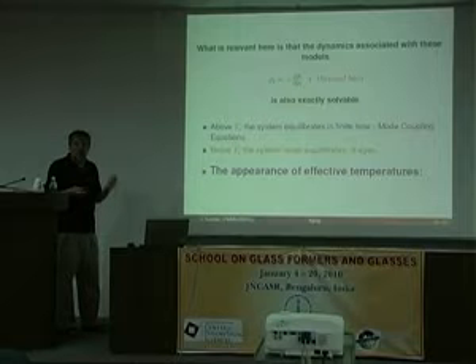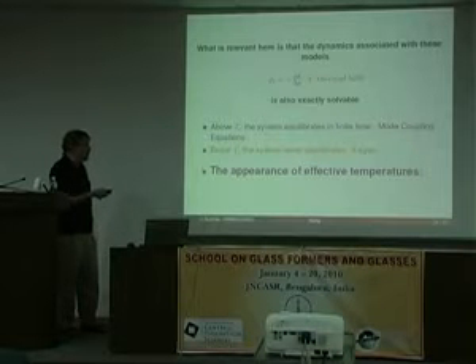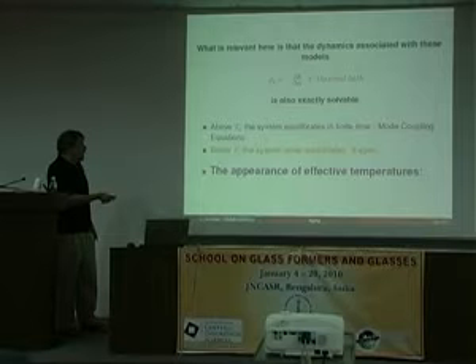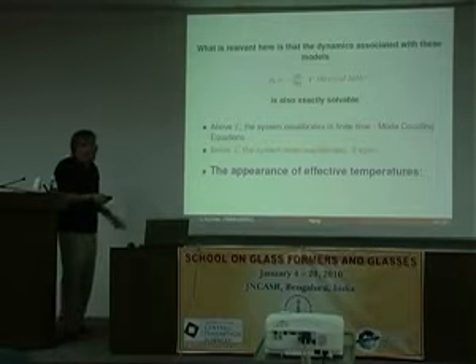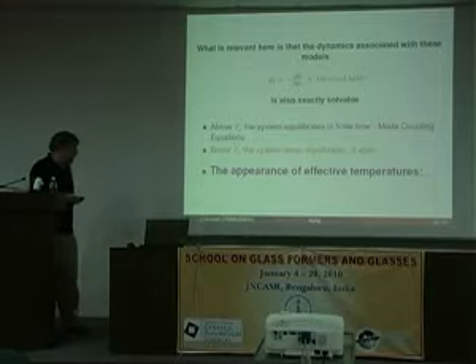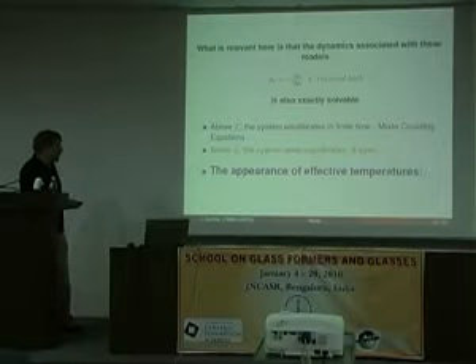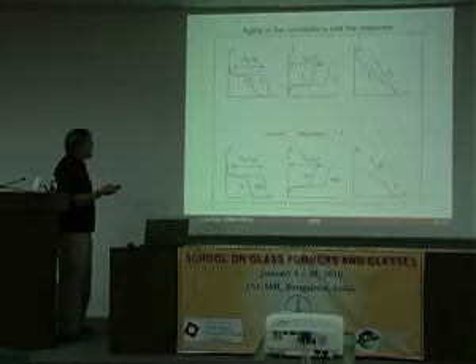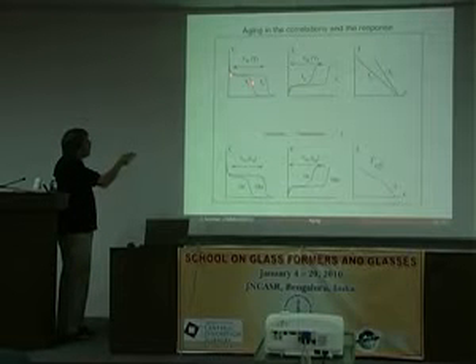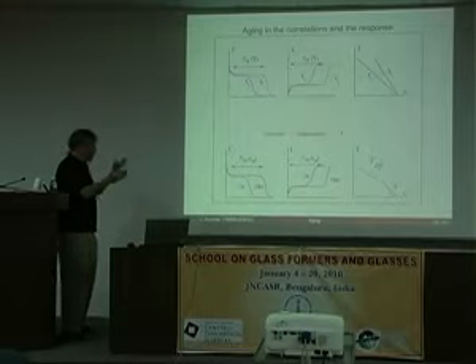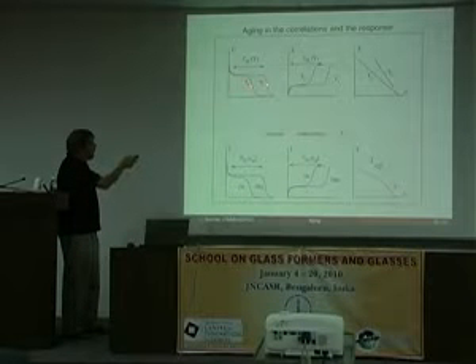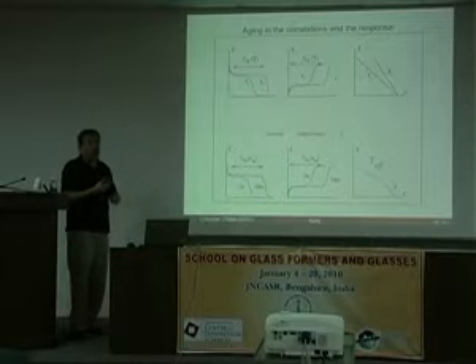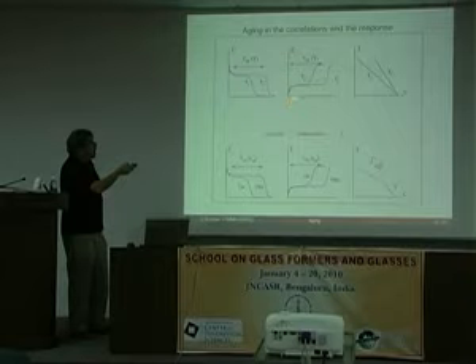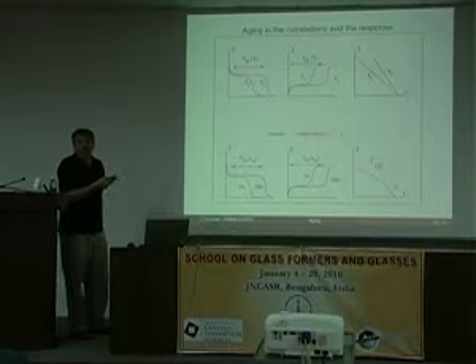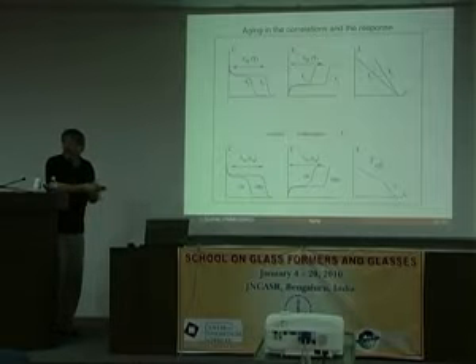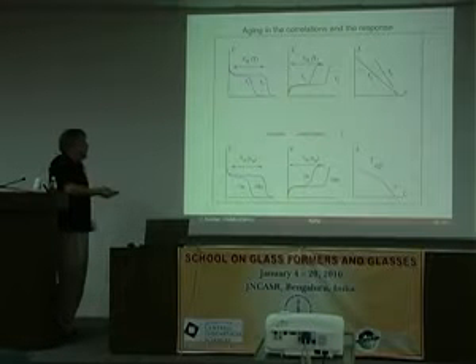And the model does this for you. You don't have any choice here. The model is well defined. You have to solve it. There's nothing to do. And you solve it, and you get aging in the response and in the correlation, just as you would get in an experimental system, qualitatively. As you approach the transition temperature, you get this time scale becoming longer. This is the mode coupling phenomenology, which was well known by that time. And you get response functions, which nobody cared to calculate in mode coupling because it's an equilibrium theory, and both things are related by the fluctuation dissipation theorem.